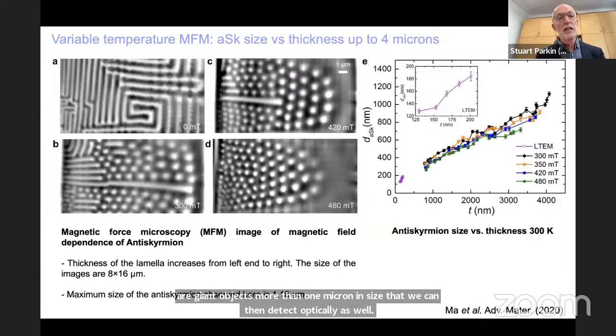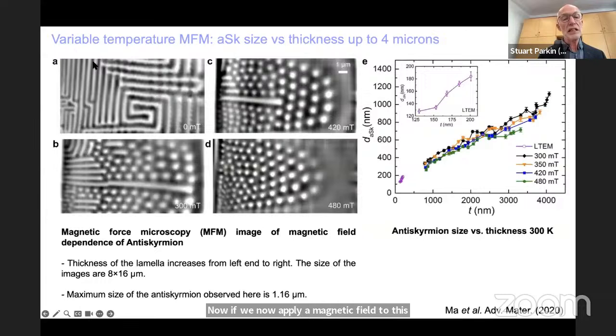Now, if we apply a magnetic field to this object out of the plane, then the helical structure shown in A evolves into the antiskyrmions. And the antiskyrmions in this magnetic force microscope look like these little circular dots, where we're just looking at the component of magnetization in the interior of these antiskyrmions. And again, you can see visually that the diameter of these antiskyrmions increases from left to right in each of these lamella as the lamellar thickness is increasing.